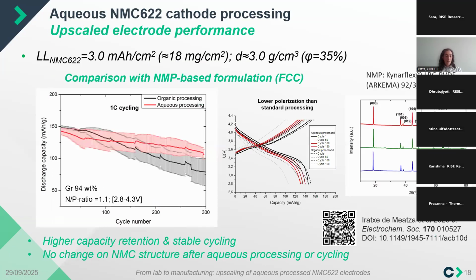So I will not stop on that point, but just to show that, on cycle life of this, which was done in full coin cells at the time, you can also find the scientific paper here as reference. The capacity retention is better for these processed electrodes, and there is not additional polarization as we see in the curve here, which is also one of the major points when looking at NMC cathode electrode processing in water.